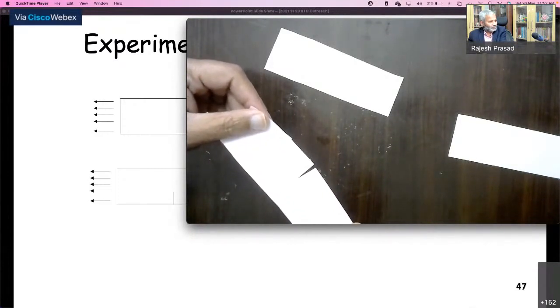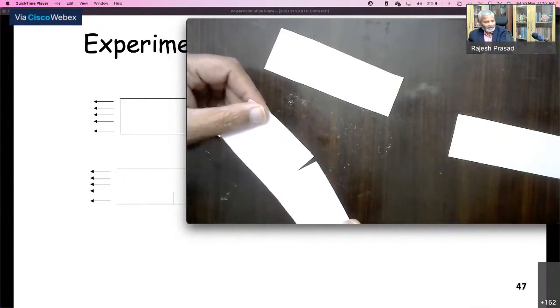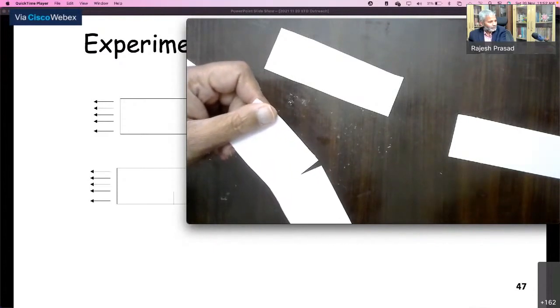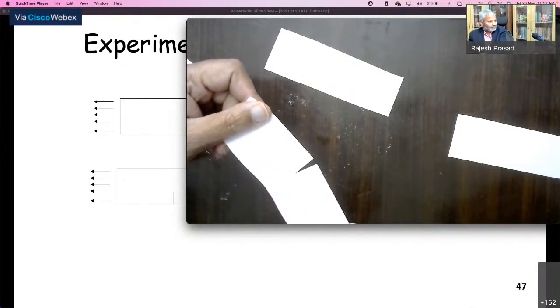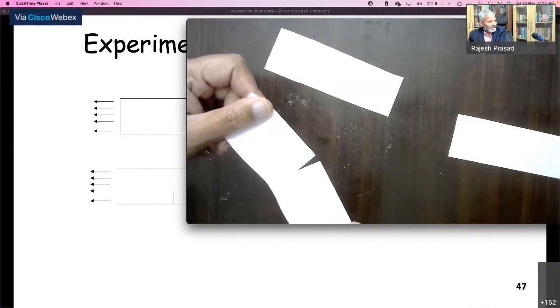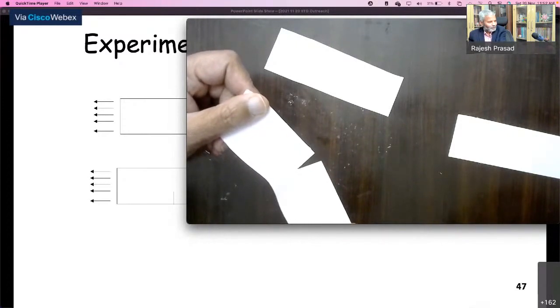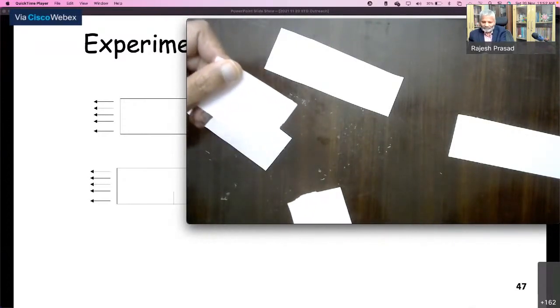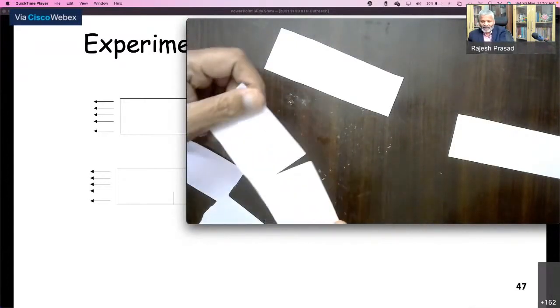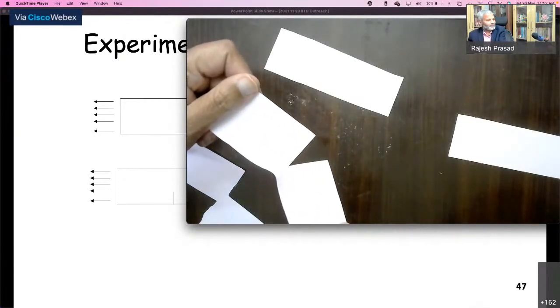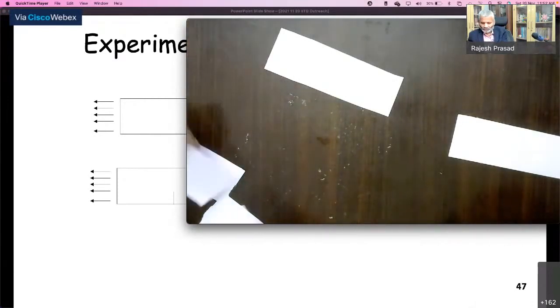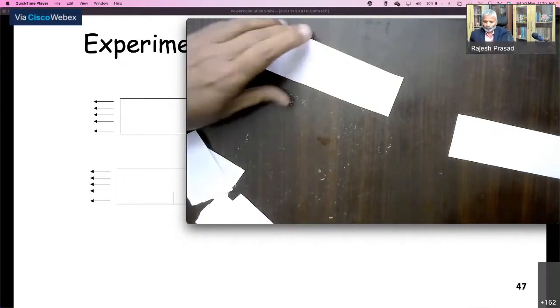See, and the other thing which you realize is that a crack is there and I'm applying a force, but it's not propagating. So it's not that a crack will always propagate under force. You require a certain minimum force to make it propagate. And if the crack is larger, that minimum force is even lower. So the higher the crack size, the lesser the force.